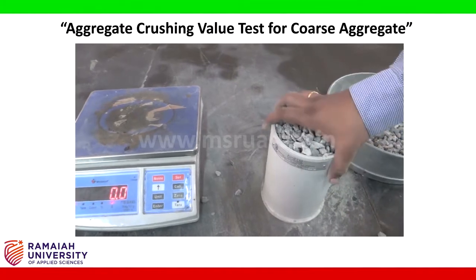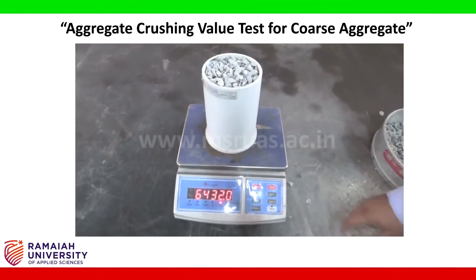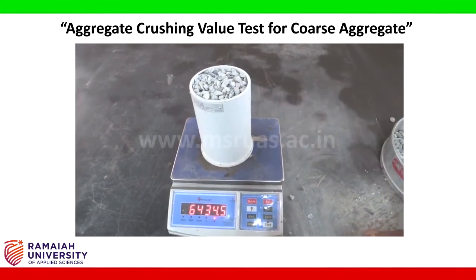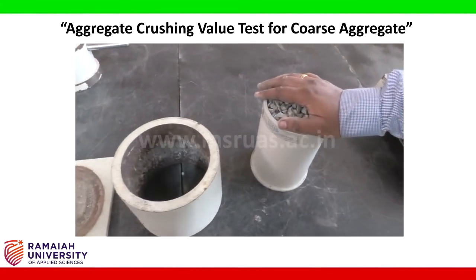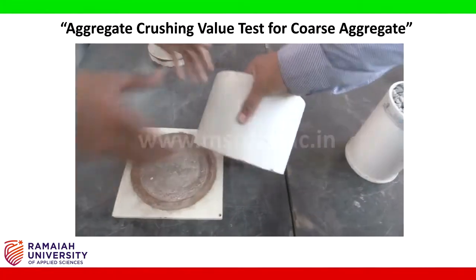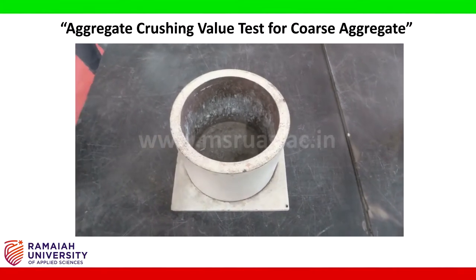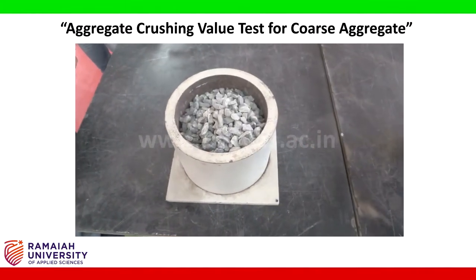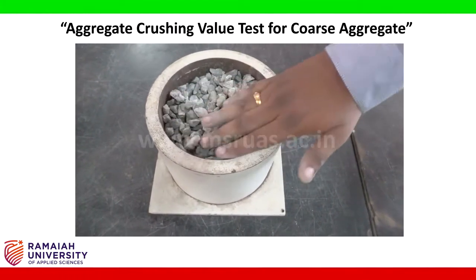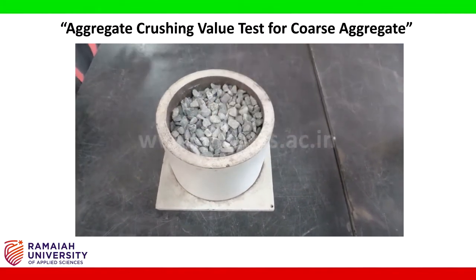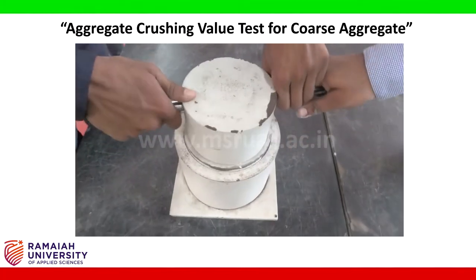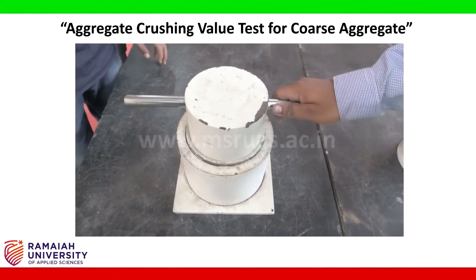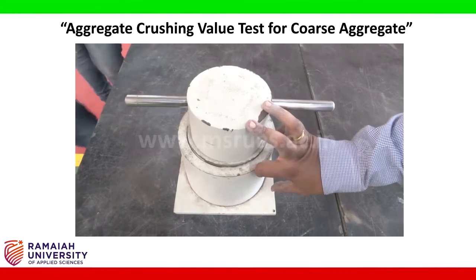After preparing the measuring cylinder, take the weight of the measuring cylinder plus aggregates and record it as W2. The difference between W1 and W2 gives the weight of aggregate present in the cylinder. Next, for the experimental setup, place the testing cylinder on the base plate and transfer the measured aggregates into the testing cylinder. Ensure the aggregate is uniformly spread, then place the plunger on top, making sure it is horizontal. This completes the experimental setup for the aggregate crushing strength test.